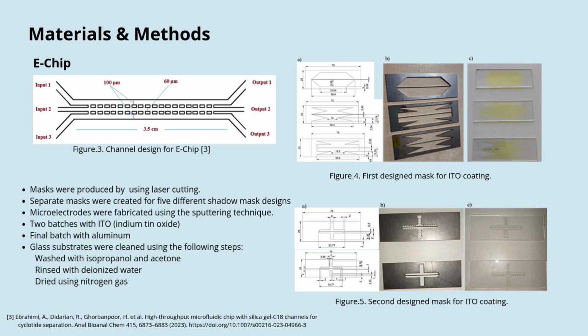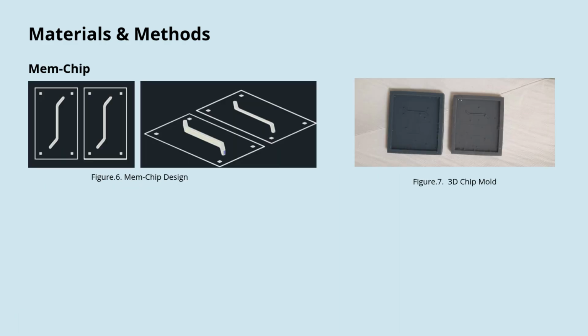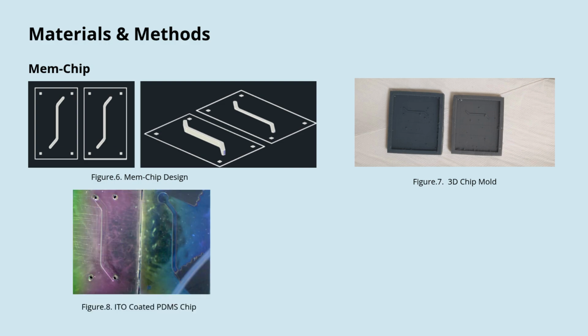After all glass slides were thoroughly cleaned with isopropanol, acetone, rinsed with deionized water and dried with nitrogen, they were sent for the sputtering process. There were three batches done for this objective. The first batch was ITO coating with RF supply, the second batch was ITO coating with DC supply, and the third batch was aluminum coating. The chip was designed in AutoCAD and manufactured using a 3D mold.